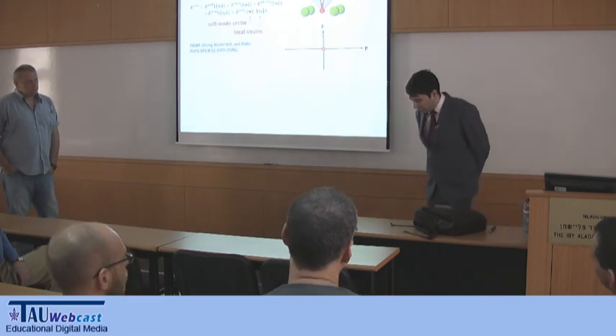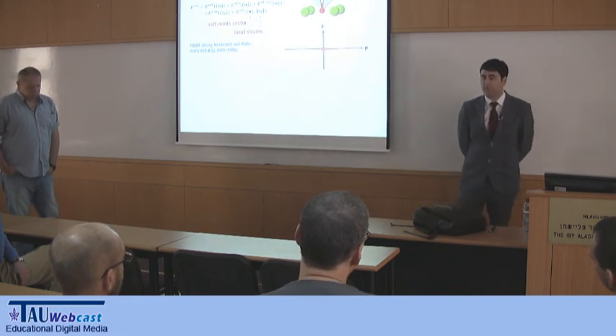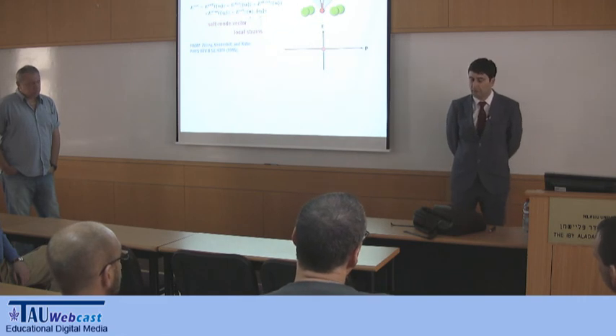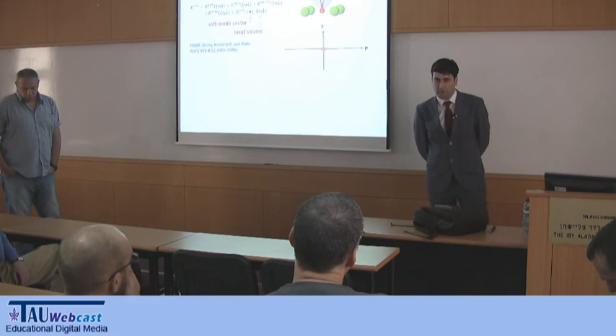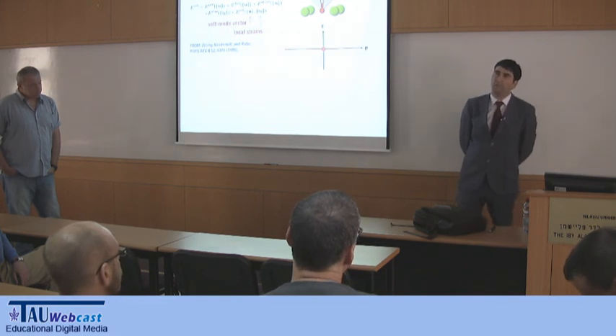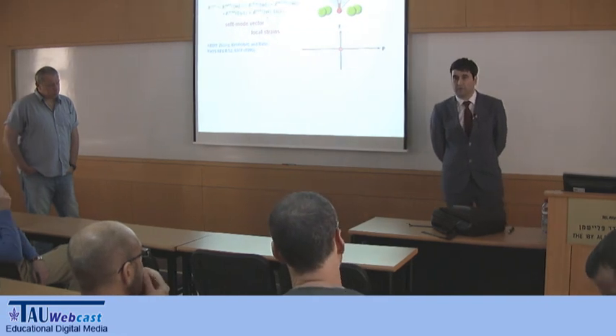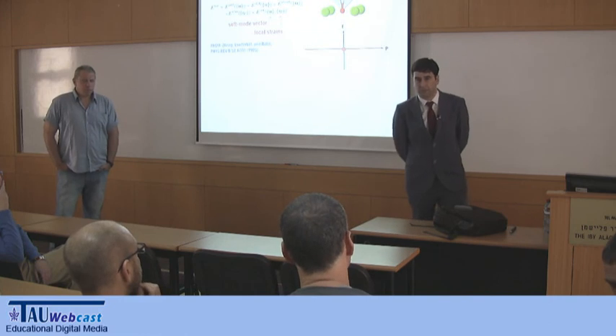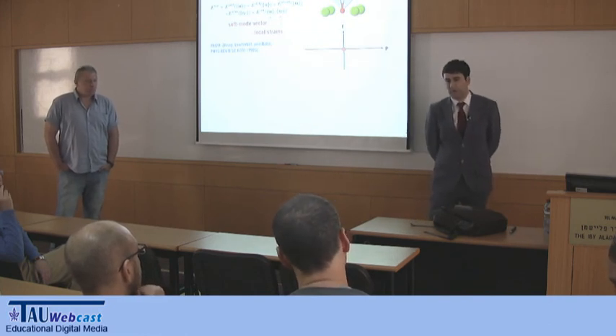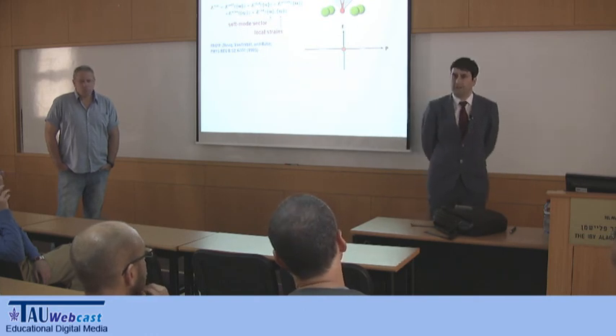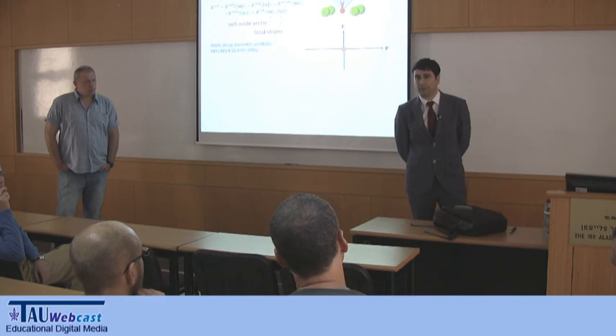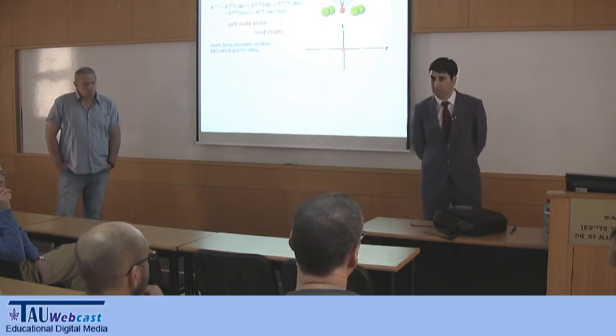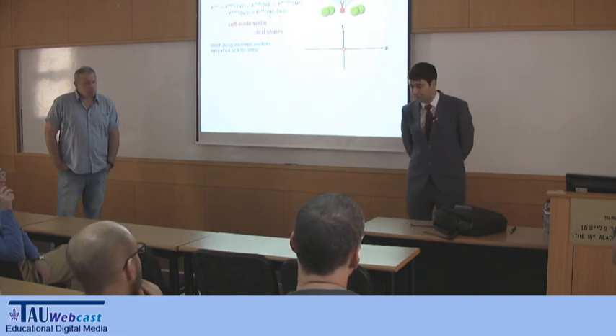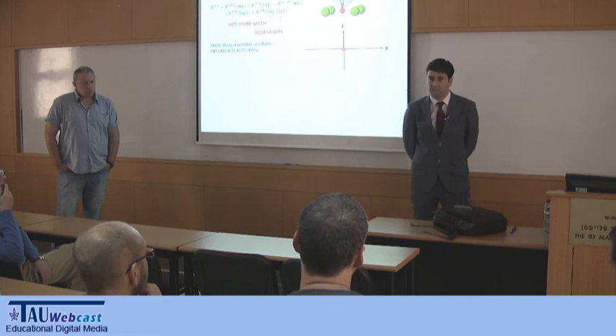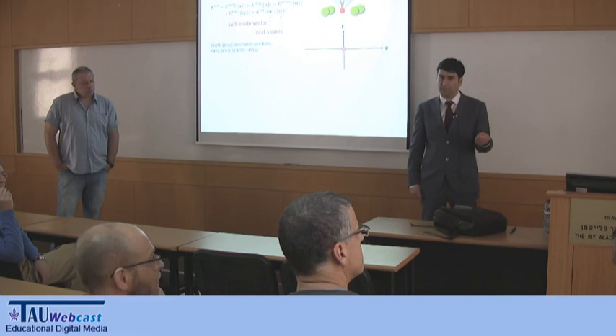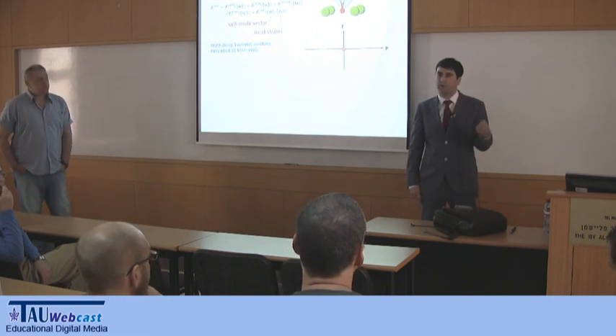Well, there is for sure a role of the exchange correlation potential, because if you change this approximation and go to LDA, you get better agreement with the experiment. This was one of the GGAs. LDA gives you a transition pressure of around double, but LDA gives you a worse transition for the misfit strain films. So in the end we went with the best compromise. Also, experimentally, it's not that clear where the transition is, because they see phases. As you raise the pressure, it seems that up to 3 or 4 gigapascals you get the ground state, then you get an area where they don't really know what they have.